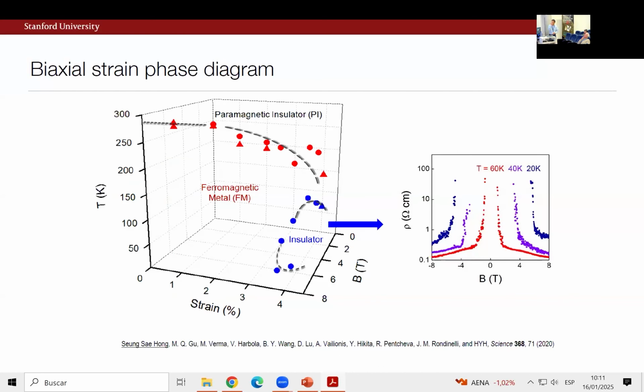So in this particular case, what we found was actually a very rich phase diagram. This is all in one membrane. It's a rather tedious thing, I have to warn you. We set the strain stage, do whatever experiments we want to do, go back up to a little bit above 50 degrees C, and then restretch and set everything. And you have to be a gambler because you want to do all of this without breaking your membrane, right?